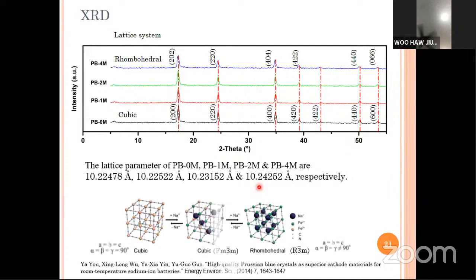From calculation, we find that the lattice parameter is increasing from 10.22 to 10.225, 10.23, and eventually 10.24, respectively. Then we try to search about it, and we found that this result is in agreement with a similar observation from another group of researchers reported in the literature, where they ran in situ XRD during charge and discharge. The insertion of sodium ion into the Prussian blue will create a little bit of distortion where the axial angle no longer makes a right angle or 90 degrees. Therefore, the cubic will change to rhombohedra.